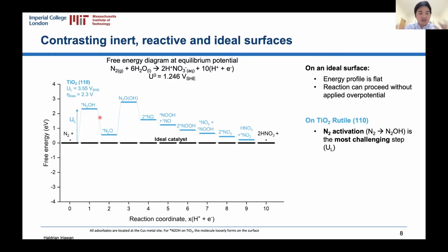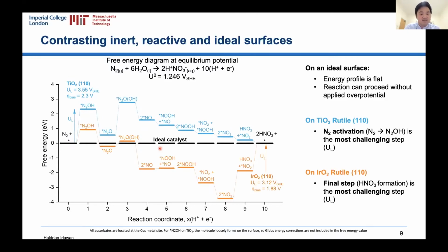So this inert surface of TiO2 can be contrasted with a more reactive surface, such as iridium oxide. For this iridium oxide, in contrast, the first few steps, such as the formation of N2OH, and N2OH, and so on and so forth, are significantly less challenging. However, the most challenging step is actually the later steps, in particular, the final step, which is when we're trying to form our product. And the computed potential is around 3 volts, or a bias of 1.8 volts. So across these materials, highly oxidizing conditions are really required to drive nitrogen oxidation.